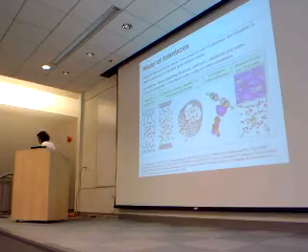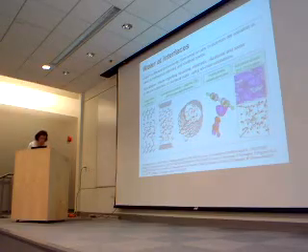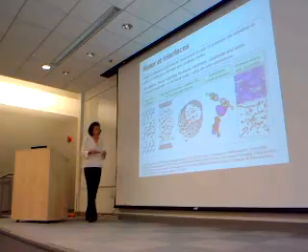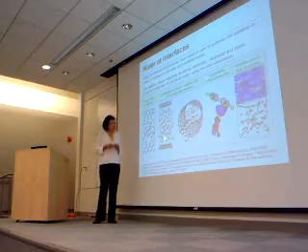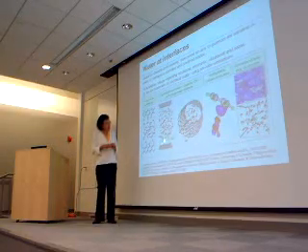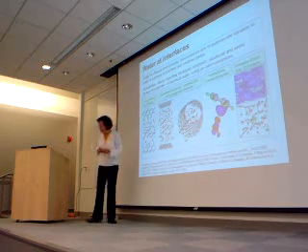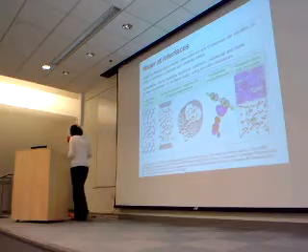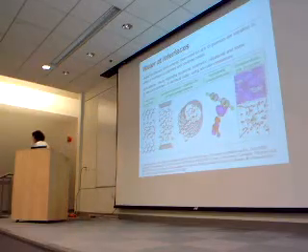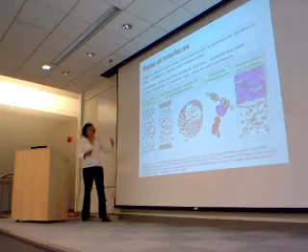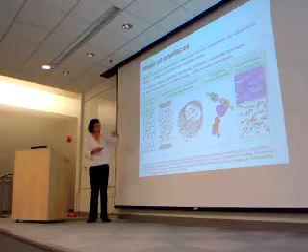On the other hand, this is also a case that highlights some of the limitations of the theory that we use. There are certainly issues in describing accurately the interaction between water, for example, and graphene, because of some dispersion interaction that may not be accounted very accurately within density functional theory. And so it's an ideal case in the sense that we don't have to fit anything.